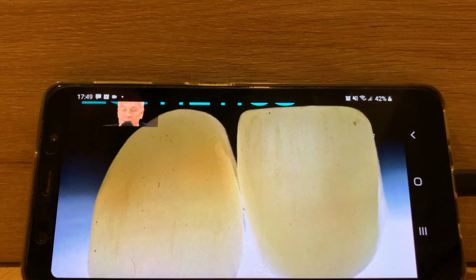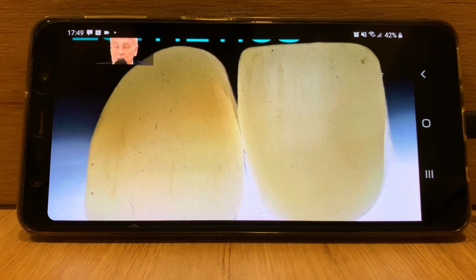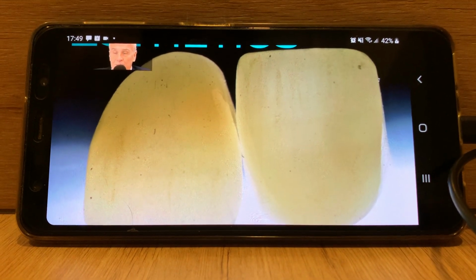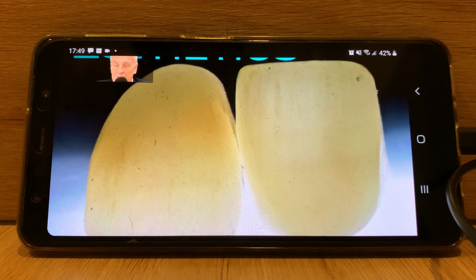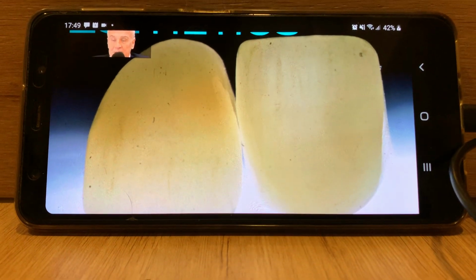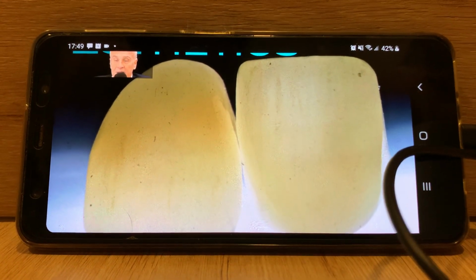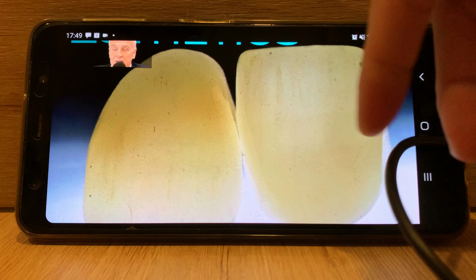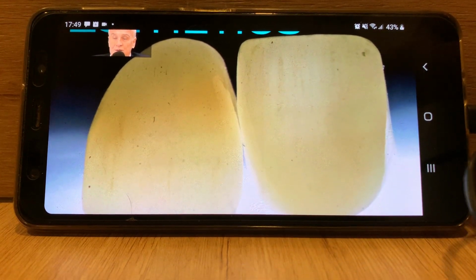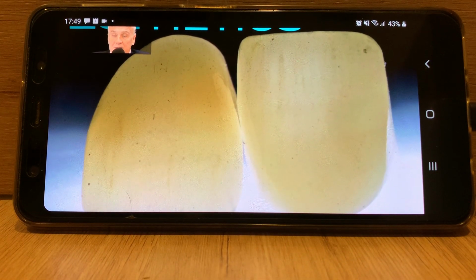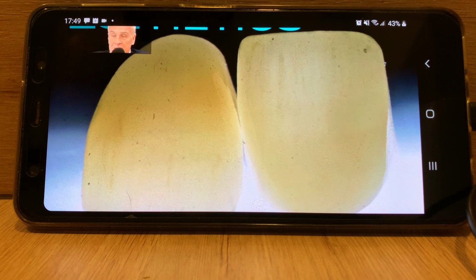The incisal edge is a 5Y zirconia, so it is about 650 with this manufacturer. It's about 650 megapascals, while the rest of the tooth, the body, 2/3 or so, is 4Y zirconia that pushes the flexural strength up to about 850.